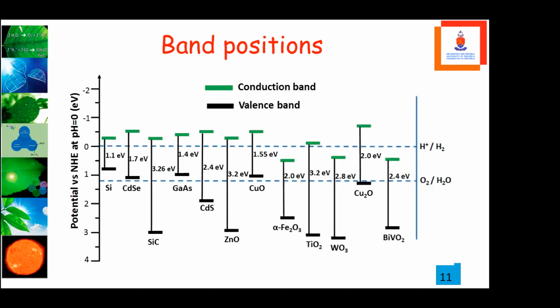But when you look at the band gaps, silicon has a nice band gap, but it is not stable in water. Cadmium selenide has a problem: cadmium dissolves easily in water and is poisonous. Silicon carbide is too wide. Gallium arsenide is suitable, but it is not stable in water. And then zinc oxide may be a bit stable in water, but the band gap is too big, so it will absorb very little of the solar energy. We are trying copper oxide, but copper oxide is not stable at all. The most attractive material amongst these is iron oxide, which we call hematite, which has a band gap of 2 electron volts, which will absorb almost 40% of the visible light, and it is stable in water.